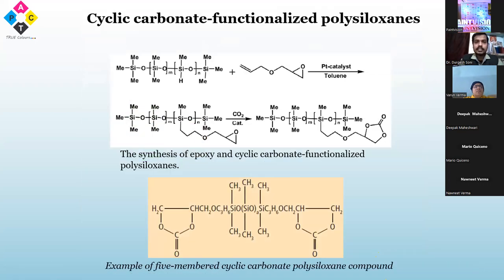Apart from this, some silicon modifications are also available, like in the figure we can see. These are the silicon modification of this non-isocyanate PU coating, in which a monomer is used having an unsaturation with the epoxy group. Again, this monomer is incorporated in this chain. And after reaction with CO2, this epoxy group can be converted into the cyclic carbonate group. Further, by curing with amine, we can obtain the non-isocyanate polyurethane.